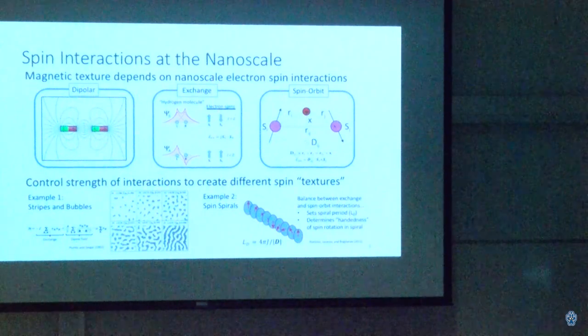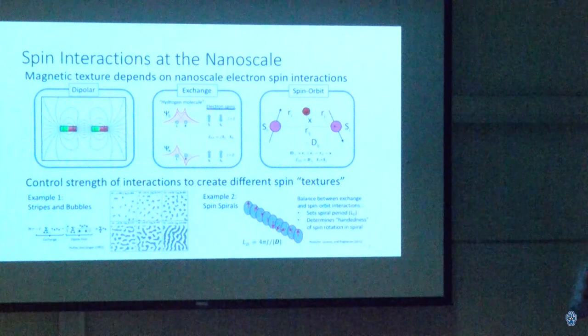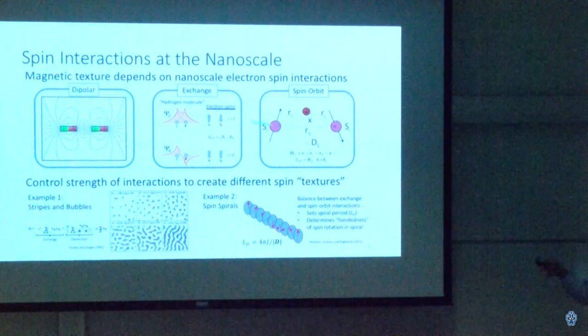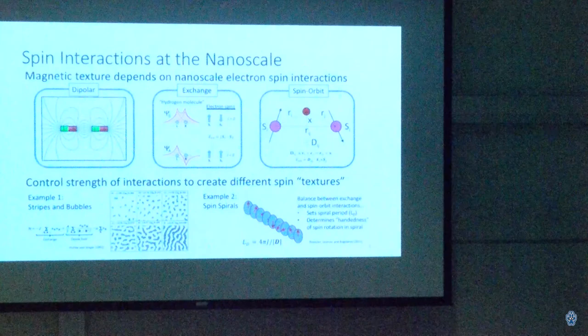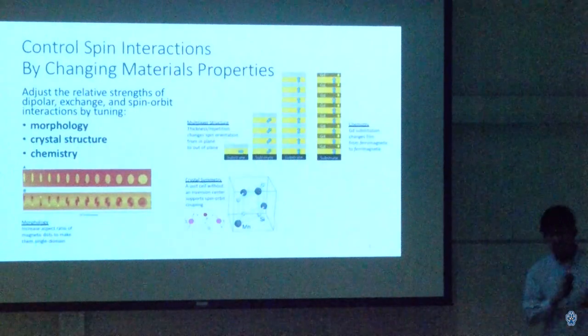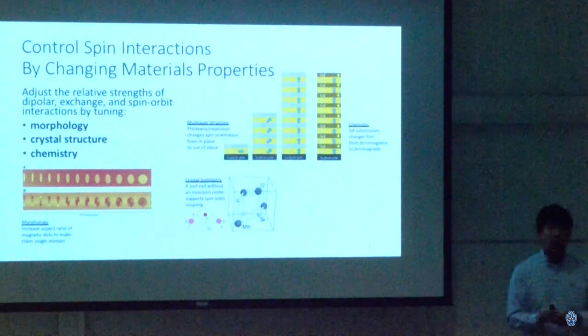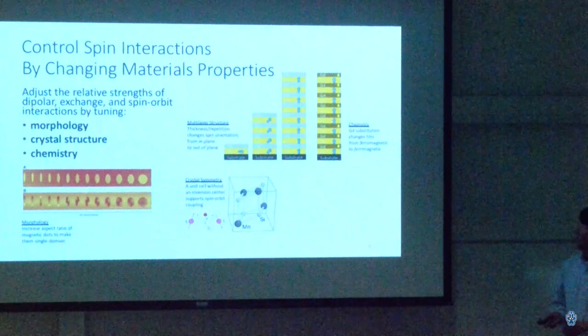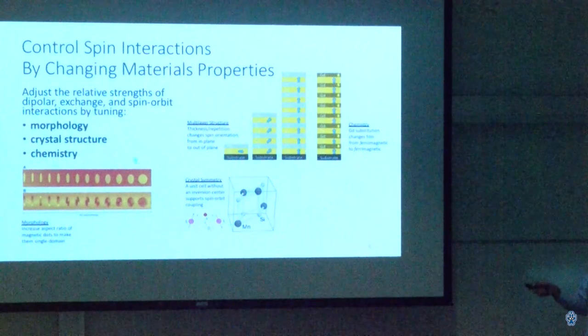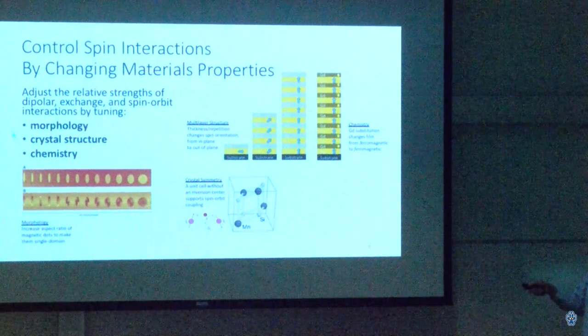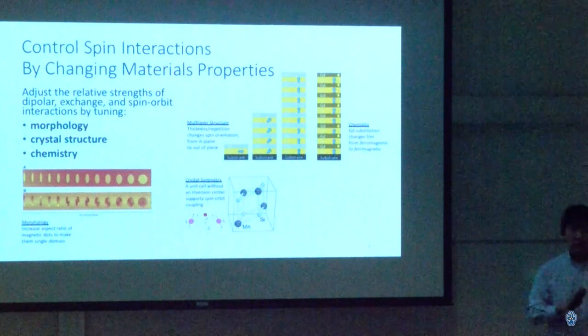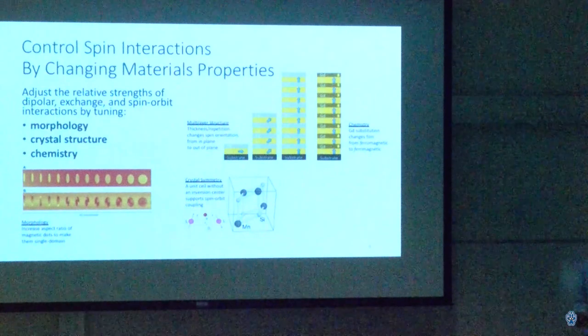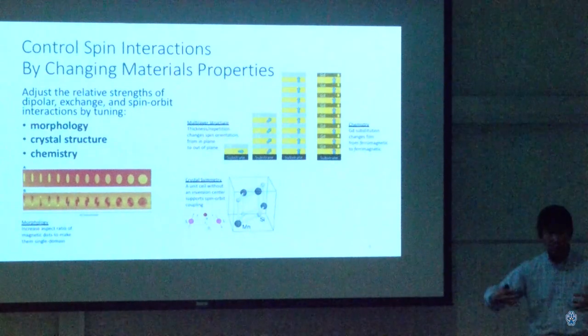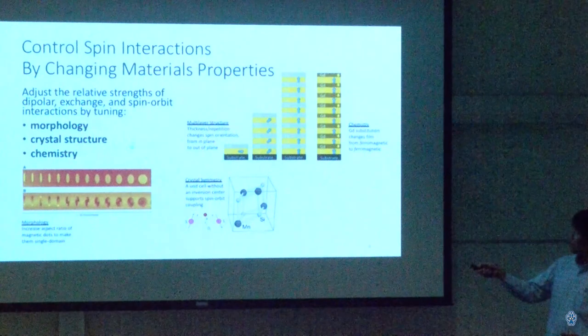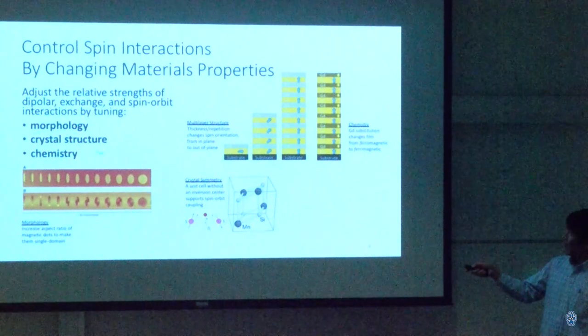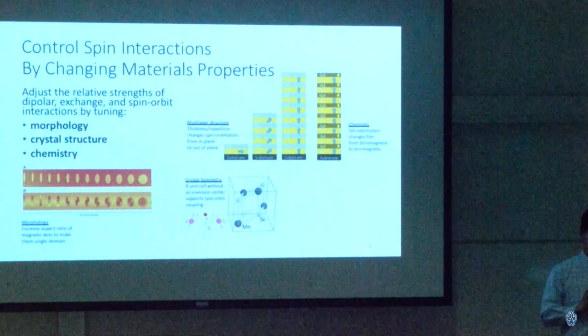So you can really change the magnetic properties of a material, especially at the nano scale, just by twiddling three different parameters. So in principle, we can do that, but how would we do that practically speaking? In this case, there are three practical things that we can do to a material in order to change the balance between those three interactions. We could change the morphology, the external shape of a material. We could change the internal crystal structure and the chemicals used to make up that material.